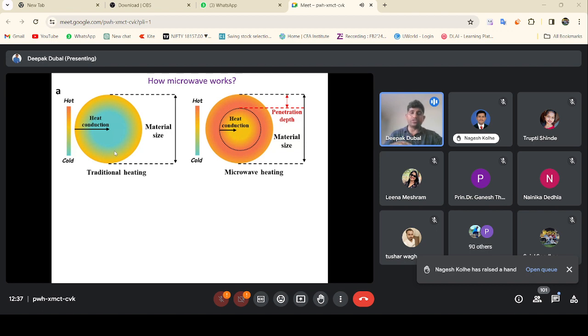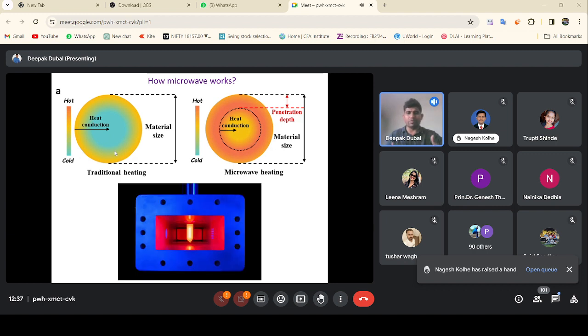Imagine that if I want to reach 800 degrees Celsius with the microwave, it takes only 8 minutes. But if I want to use the traditional heating method, it takes almost 2 to 3 hours just to reach the temperature. And you can do this simple experiment at home.